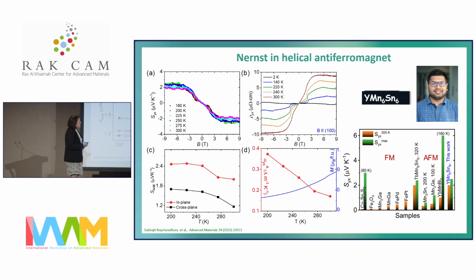And indeed, now you see here are ferromagnets and here are antiferromagnets. These are common ferromagnets, and these are the values which people thought you expect in magnets for the Nernst effect. And now you see that all these topological materials are much higher in their Nernst effect, even the antiferromagnets, which people believed had no anomalous Nernst effect. So in this sense, these are all nice materials which we should systematically investigate for getting really high efficiency in energy conversion in magnetic materials using topology, simply looking for crossing points at the Fermi energy.